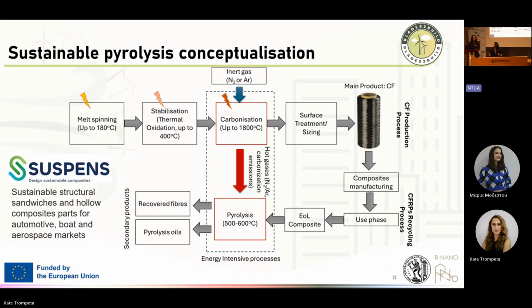And from all these steps, we take the carbonization, which is a procedure that goes up to 1,800 degrees, and we try to recover the hot gases, or generally the heat produced from this process, and to deliver them to pyrolysis by designing a new pilot line, a new system that could use the heat from the carbonization for the pyrolysis, which takes place at 500 up to 600 degrees. By this, we have a closed loop. Actually, we are combining both the production of the carbon fibers with the reclamation of carbon fibers. So in parallel, we have production and recycling.